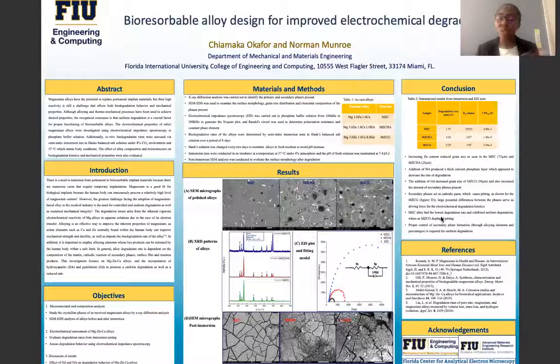And we also found out that the large amount of secondary phases present increased degradation rate because the secondary phases could begin to act as cathodic pairs, and this will cause pitting. Also, generally, we found out that the MZC alloy had the lowest degradation rate as tabulated here, and we could also see that the parameters from the EIS Nyquist plots are represented here, and it also had the highest resistance, which is a parameter directly related to the degradation rate.